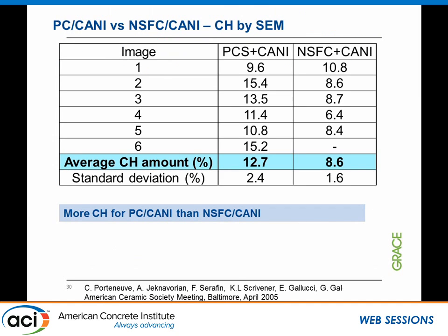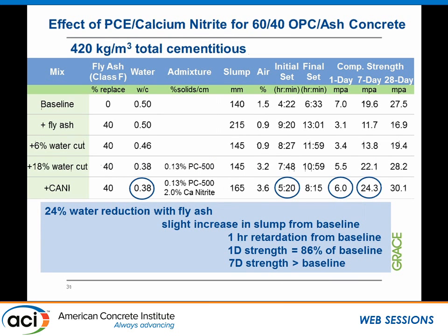Same thing as when we're looking at the calcium hydroxide content by the SEM. Once again, the polycarboxylate gave you a much higher amount of calcium hydroxide in this case. So what we see in there is really that there are some hydration kinetics differences between the polycarboxylate and the calcium nitrite. So now we want to try this with our mix that has the fly ash in it. So what does it happen?